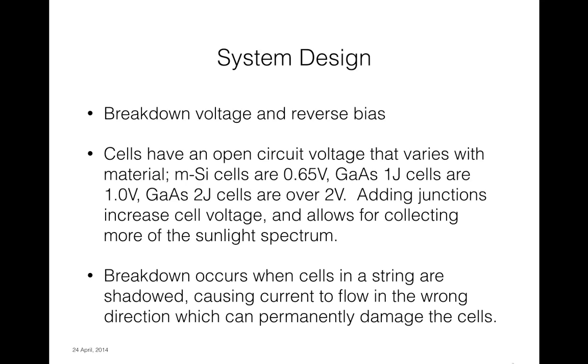Now, some of these solar technologies lend themselves much more easily to that kind of interconnect than others. Crystalline silicon cells are designed to be strung together in a series parallel form. They don't like to be cross-tied because the cells don't have a commercially available interconnect structure to do that. The gallium arsenide cells accommodate that completely. And so we find that there's a big benefit to being able to do this kind of massively parallel cross-tie interconnect. And largely it's for two reasons.